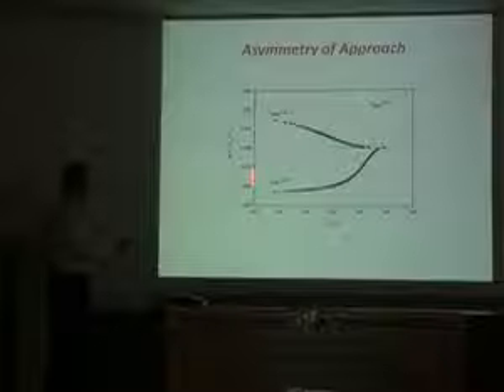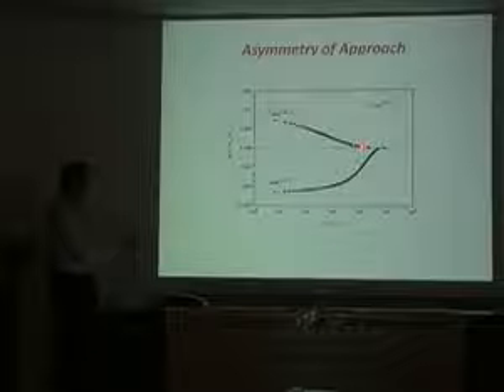If it were a linear process, this would be a mirror symmetric result, because everything's happening at 35 degrees. Okay? So, obviously, the term asymmetry suggests that it's not going to be a mirror image. And this is a plot of Kovacs's data, where we plot the departure from equilibrium as a function of the log of the time after the quench. And what we see is in the down jump, we get this kind of behavior. We get a fairly rapid approach. We can see it's almost into equilibrium in 10 to the 4th seconds.